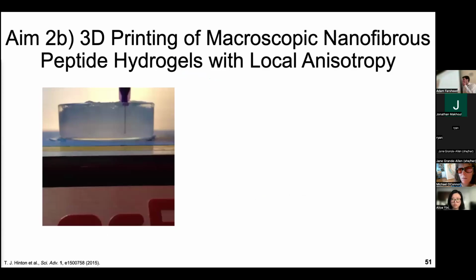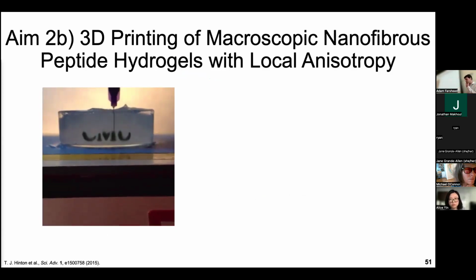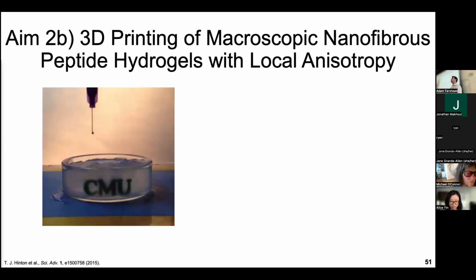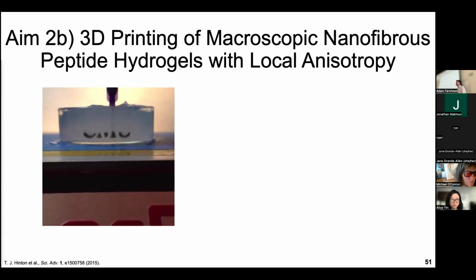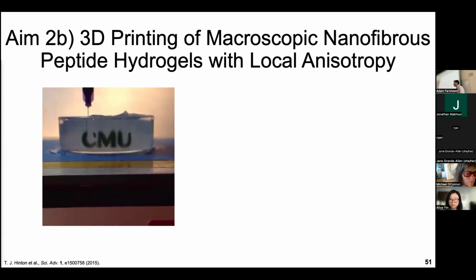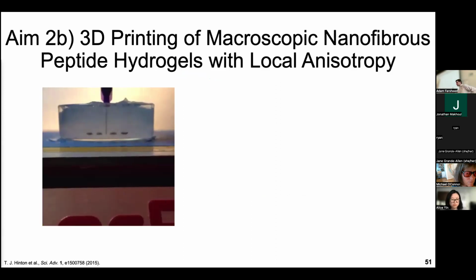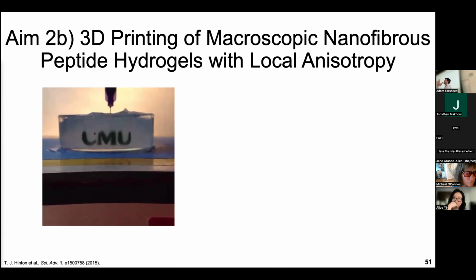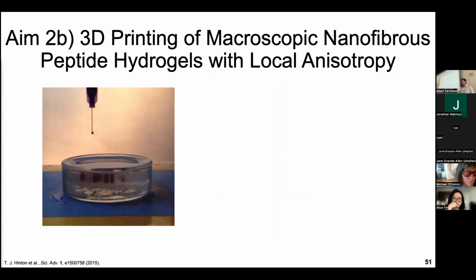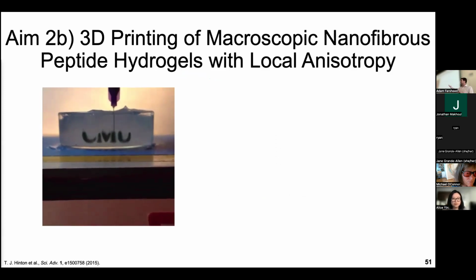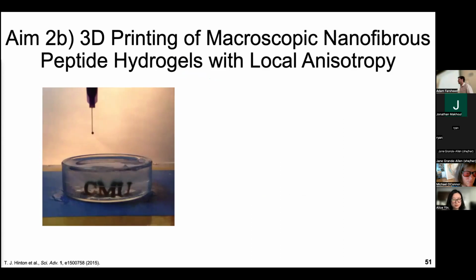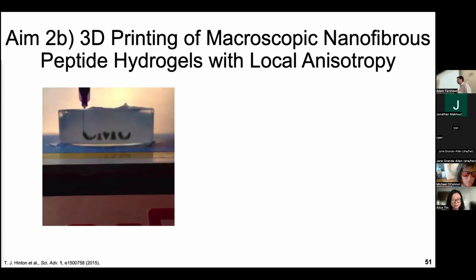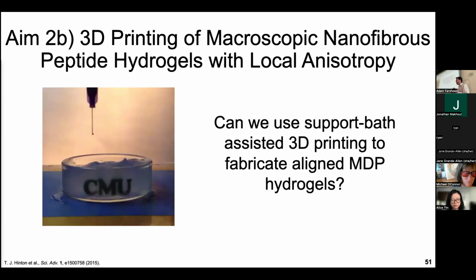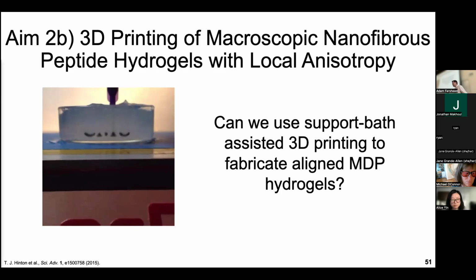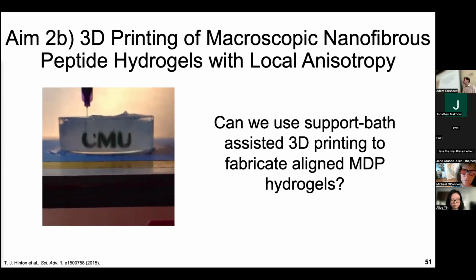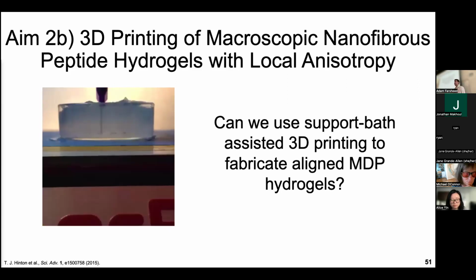hydrogels? And so what we turn to is this technique called support bath extrusion printing, where when you work with liquid-like materials and you want to print them, you can either do the materials optimization that I talked about in aim 1, or you can use this fancy technique where you're actually printing your material into a gel in and of itself. And so what that enables you to do is support as you print your structure until you're done printing. And then in this case, the temperature is turned up and the melting of that gelation bath is able to occur, or the support bath is able to occur, and you can get this kind of macroscopic structure. And so what I wanted to do was basically take this technique and append it to what we just showed in aim 2A and say, can we use this to create aligned macroscopic structures with our MDPs?